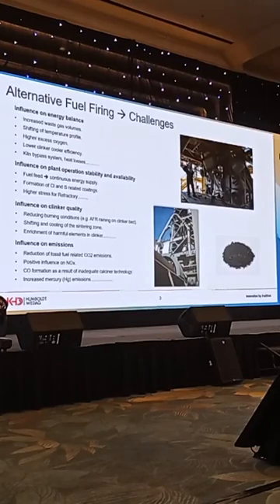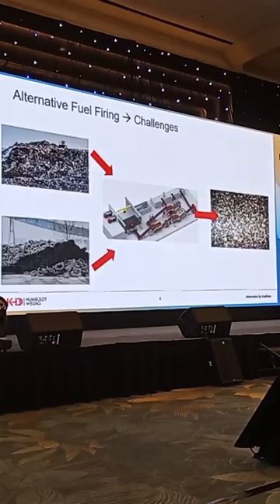Okay. When we look at these challenges to the system itself, you have to look also at other challenges when using alternative fuels, and this is the alternative fuels themselves. So when you're thinking, okay, we can use it, we are happy to use it, we see the challenges, this is okay for us, you also have to think about getting the alternative fuels from the waste storage areas outside in the right amount. We are talking here about values of minimum 10-15 tons per hour, going up, depending on the plant size and the substitution rate you want to use, to 40 or 50 tons per hour. This means values of up to about 1,000 tons per day of alternative fuels, and this has to be handled and has to be available on the market.